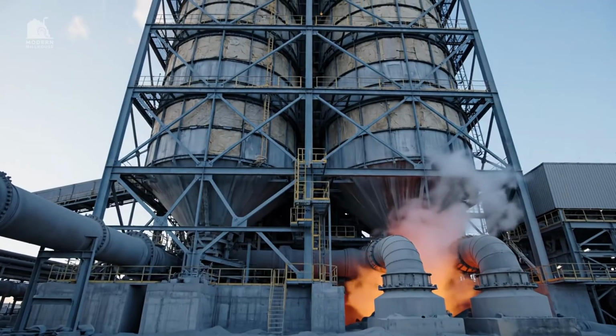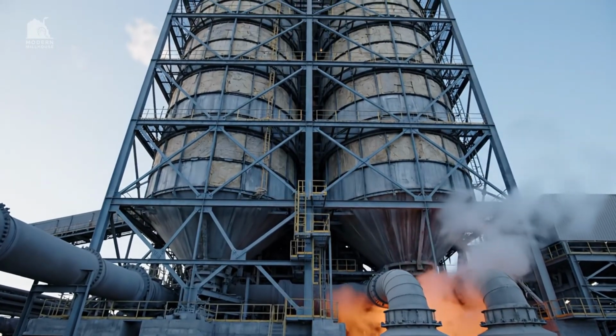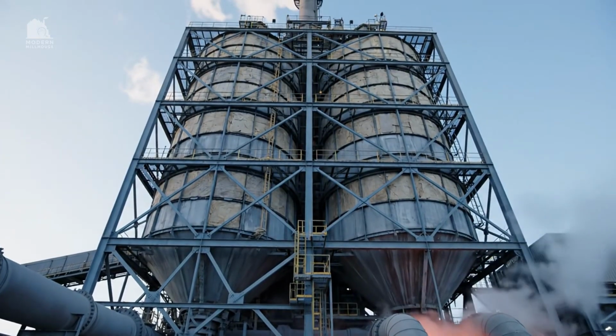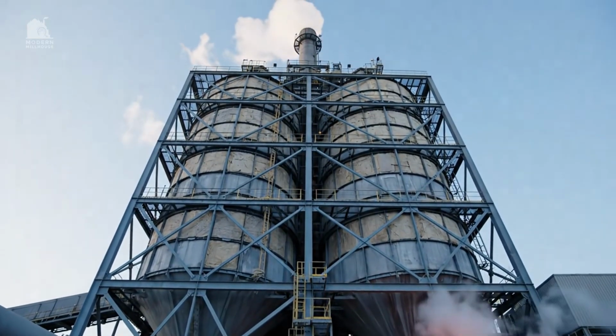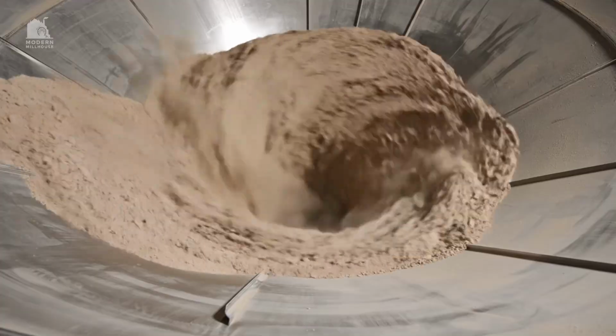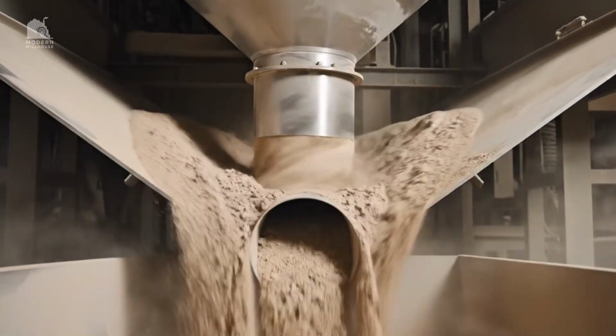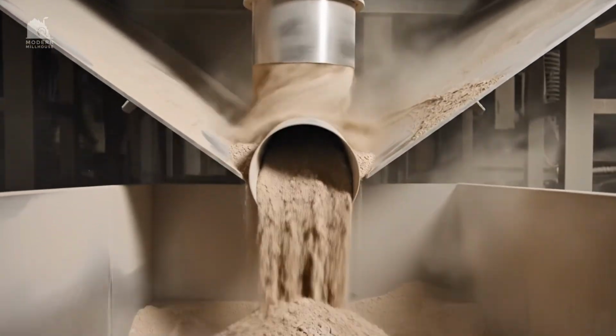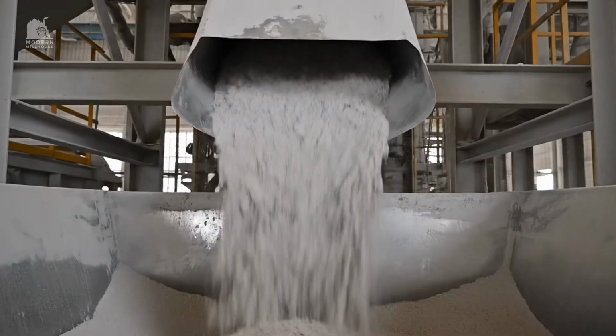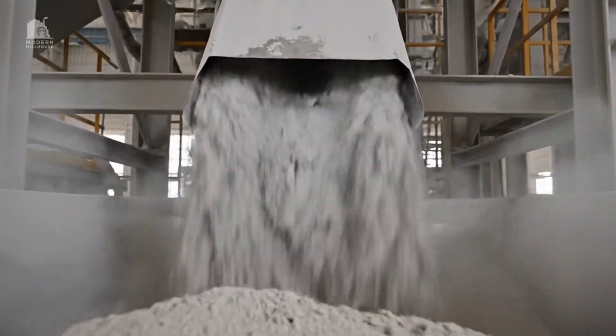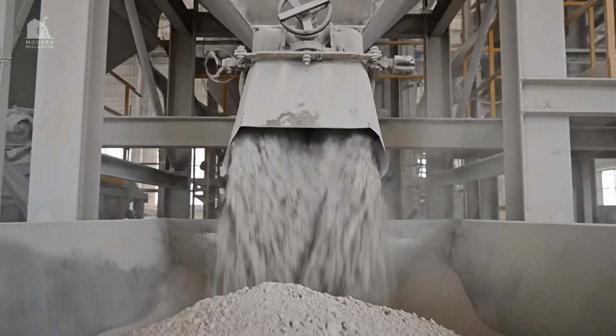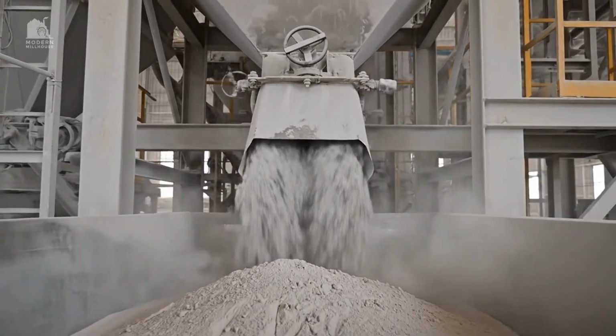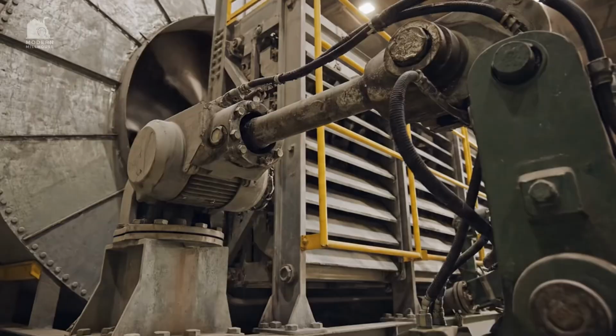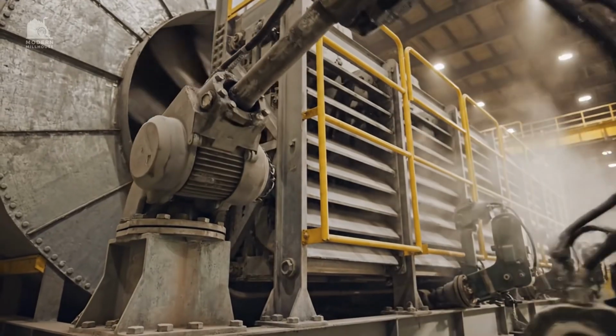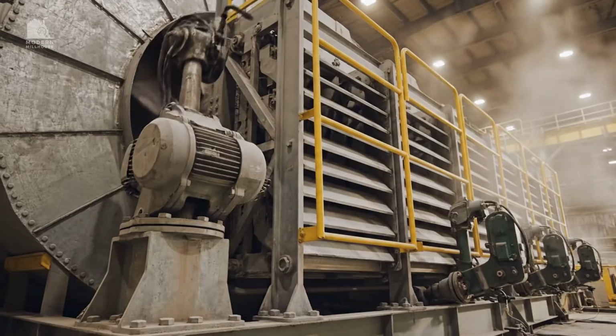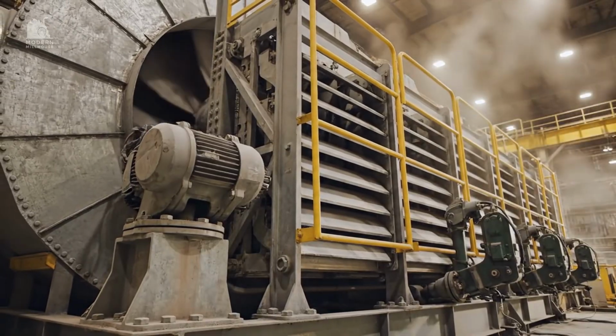The preheater raises raw meal temperature rapidly by exchanging heat with hot exhaust gas leaving the kiln. Cyclones separate solids from gas in seconds, letting meal fall downward while gas continues upward through the tower. Each stage lifts temperature further, so less fuel is needed later, and the kiln becomes more energy efficient. Draft control keeps the entire system stable, preventing backflow, dust buildup, and flame instability downstream.